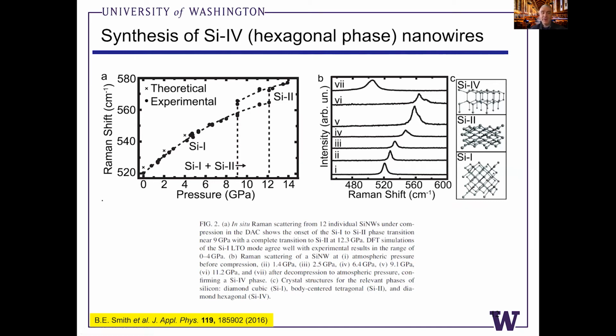Just to illustrate what's possible with pressure, this is a really neat technique. And for instance, you could start with a silicon material. Everybody who's worked with silicon has seen that it's a cubic crystal structure. You've got the same crystal lattice as diamond. And if you squeeze silicon to above 10 GPa, you can make a tetragonal phase. You can effectively compress the cube in one direction. But if you relax that pressure, surprisingly, you can recover a hexagonal phase of silicon.